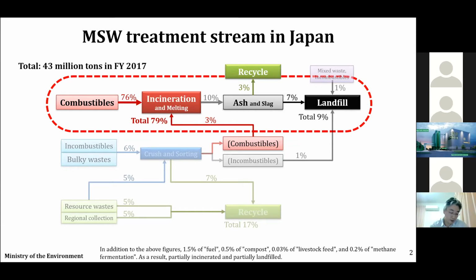As a result, thermal treatment residues, ash and slag, including fly ash, are generated at about 4 million tons per year. Currently, 3% of the 10%, that is 30% of the residues, are recycled, and the ratio of recycling is increasing little by little. However, 70%, including most of the fly ash, still goes to landfill. I consider one of the reasons would be the characteristics of fly ash.